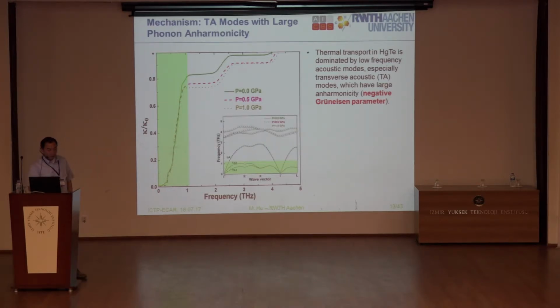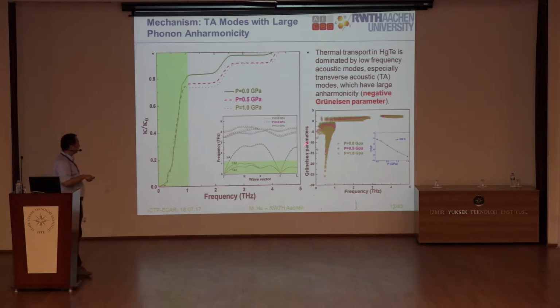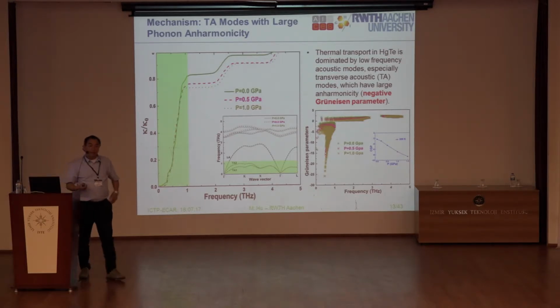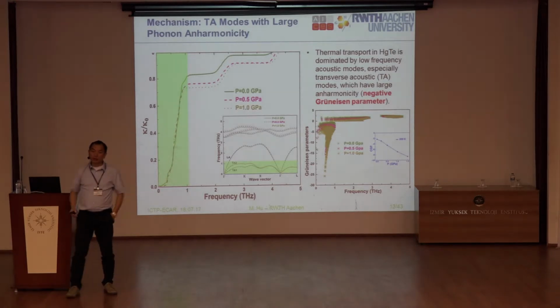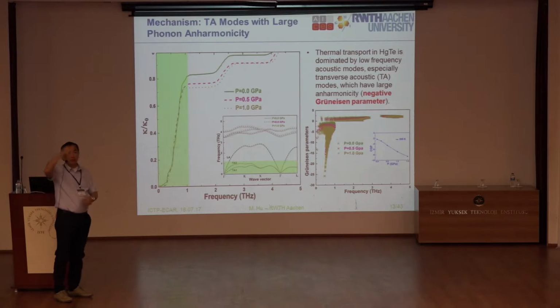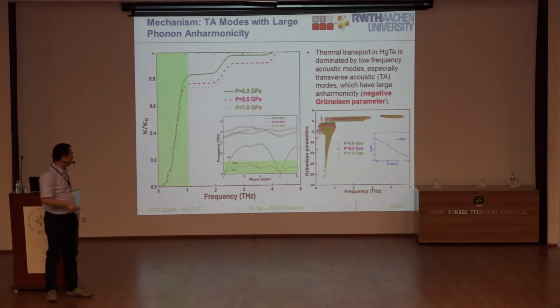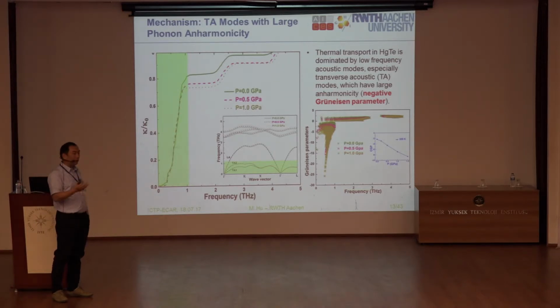So actually we found this is the dispersion. You can find that up to about 1.2 terahertz, the thermal conductivity accumulates up to 80%, and the phonon dispersion curve just cuts across the two TA modes. We also link this with the negative Grüneisen parameter of the TA modes. We know that the Grüneisen parameter can characterize the phonon anharmonicity in materials, and if the Grüneisen parameter is large in magnitude, it means the phonon anharmonicity is strong, right? And we also know that some materials do have a negative Grüneisen parameter.